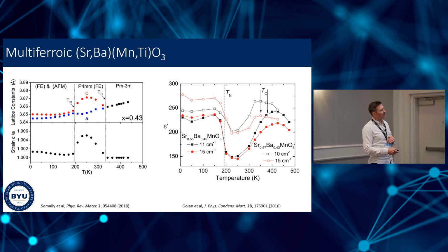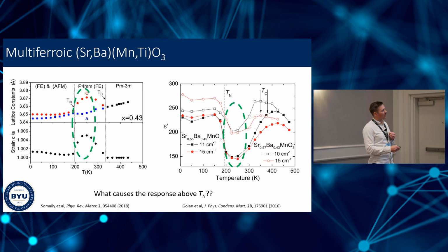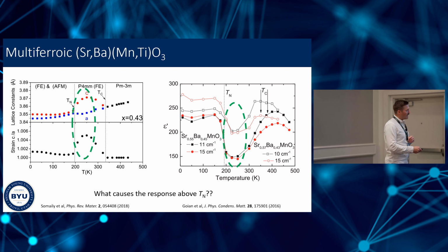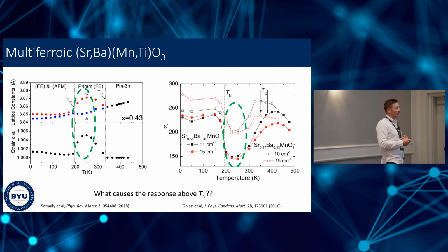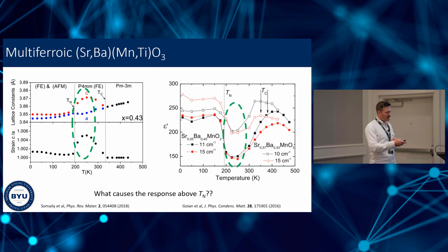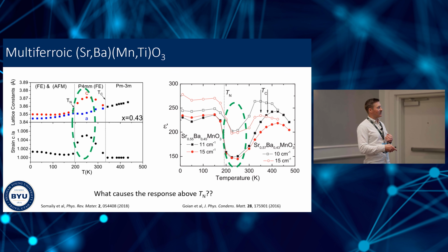All right. We can also see something similar in the dielectric constants here. What you might notice, though, is that this C over A ratio and this dielectric constant begin to show a change well above the Néel temperature. So here's the Néel temperature, about 200 Kelvin. Around 300 Kelvin, the C over A ratio turns over. The C lattice parameter turns over, all right? And yet, this C over A ratio, that change is supposed to be the evidence of the multiferroic behavior in this material. So again, this is just indicating that this multiferroic behavior begins even when we're not in the long-range ordered antiferromagnetic state, okay?